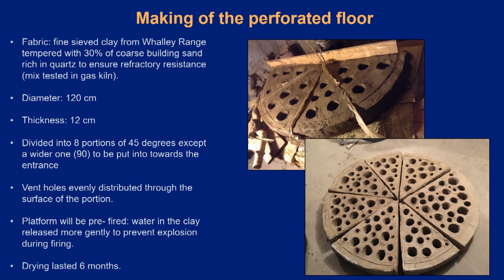Considering a 10% shrinkage rate after drying, we have added 10 centimeters to the diameter and 2 centimeters to the thickness. We agreed to build the platform by making 8 portions averaging 45 degrees each, except for one twice as wide, which will be placed at the entrance of the combustion chamber. This has been decided for 3 main reasons.